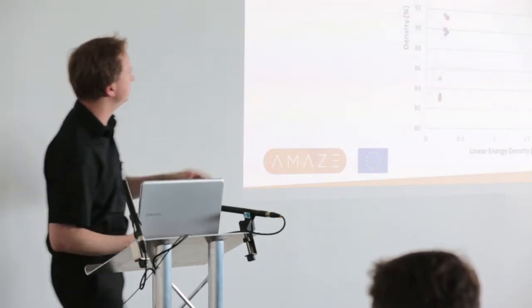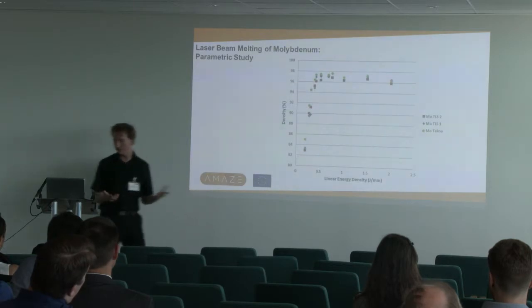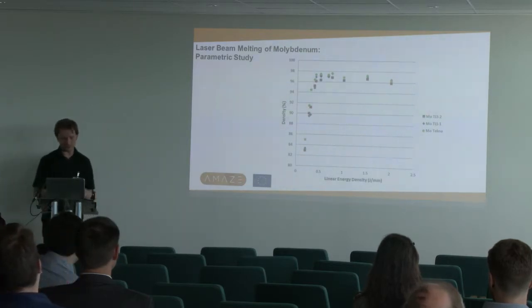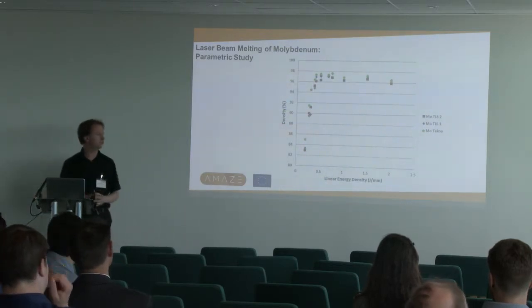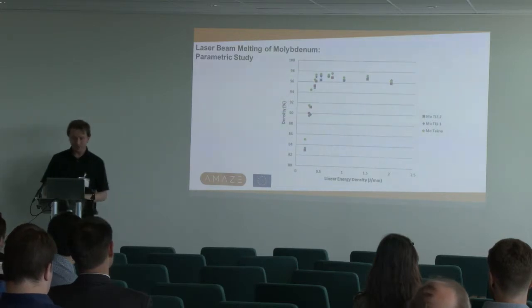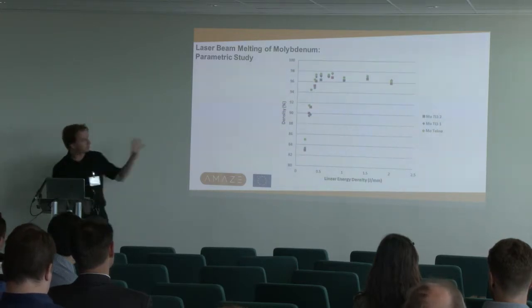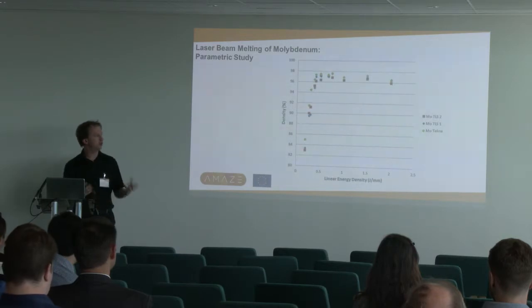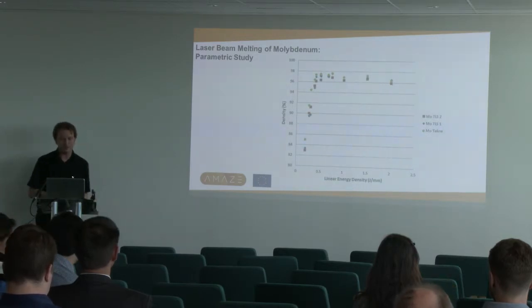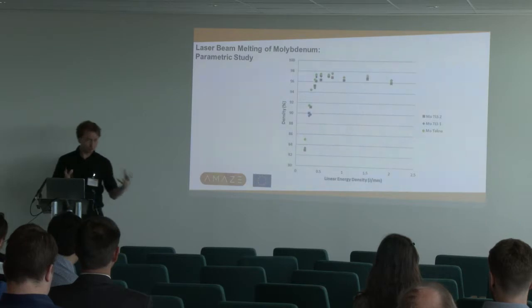When we carried out our parametric study, here are some basic Archimedes density measurements with those 3 different powders presented back to back with just, again, simple linear energy density. So this is just the power over the speed. But it illustrates that the nice spherical powder, the Tekna powder, was outperforming the other 2 in terms of just porosity pretty consistently.